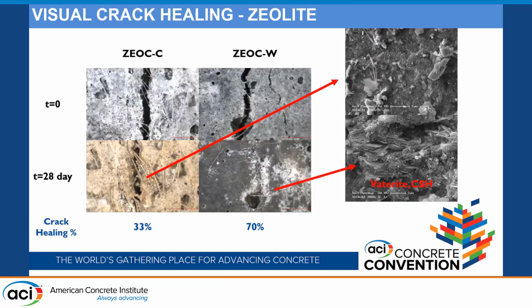When we look at the zeolite, we didn't observe efficient crack closure in samples with bacteria, but on the other hand, in samples containing zeolite without bacteria cells under water curing, we observed 70% crack closure. And we observed 33% crack closure in the samples without bacteria cured in nutrient medium. The high crack closure was observed in water-cured samples. It can be related to the reactivity of the zeolite. Zeolite can be classified as a natural pozzolan. Moreover, cation content and ease of cation exchange in the zeolite are important for short-term reactivity.